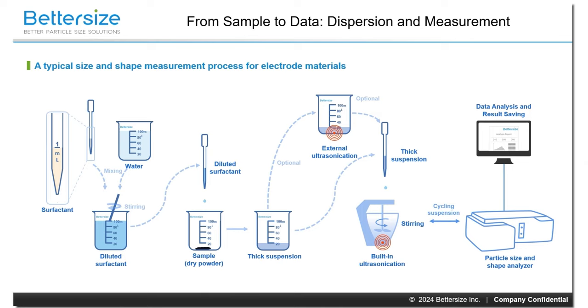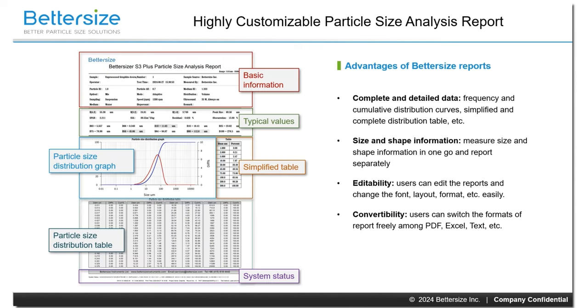In the end, a thick suspension would be dropped into the dispersion module BT803, then being stirred and ultrasonicated there. Well-dispersed particle suspension will circulate between the dispersion module and the Bettersizer S3+ main unit. Data collected will be analyzed in Bettersizer software. After a test, now the data is collected. Here we have unprocessed graphite tested with Bettersizer S3+ and got a particle size report in this way.